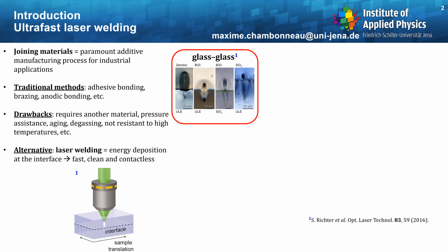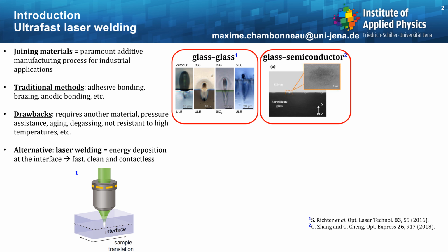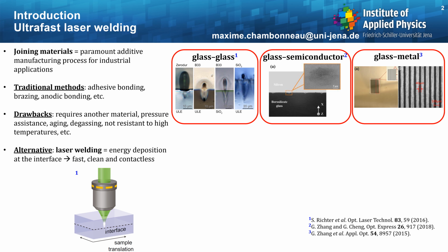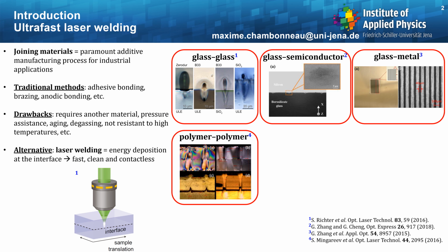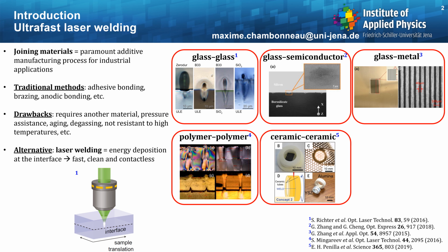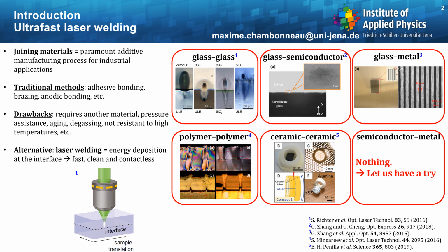As an alternative technique, the laser welding technique has been developed recently. Laser welding consists in energy deposition at the interface and provides a fast, clean, and contactless way to join materials. This technique has been shown to be applicable in different material configurations such as glass-glass, as you can see here, glass semiconductor, glass metal, polymer-polymer, and more recently ceramic-ceramic. However, in the case of semiconductor and metal, there is nothing too convincing so far. So why? Let us have a try together if you don't mind.